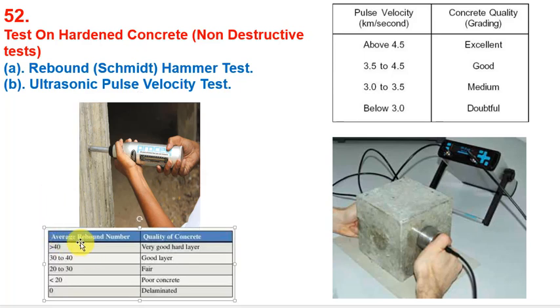So this table is showing average rebound numbers. If the average rebound number is greater than 40, that means that your quality of concrete is very good and the layer of the concrete is very hard. If the average rebound number is between 30 to 40, then the quality of concrete is good. If it is between 20 to 30, then it is fair. If it is less than 20, it is poor concrete. If it is zero, then you know it's delaminated concrete.